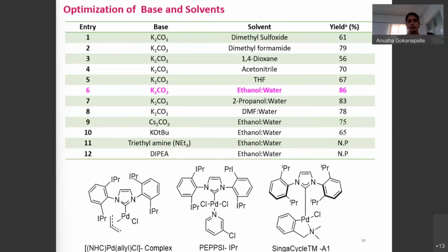These are the palladium NHC complexes, and these two are palladium PEPPSI complexes. Here we are comparing these. Two are available in our laboratory, and this one I have purchased online, and we compared all these palladium NHCs for Suzuki coupling reaction. These two are already reported catalysts. That's why we chose the SingaCycle one. There are no reports on the SingaCycle one. That's why we chose it. These three palladium NHCs gave more or less the same yields.